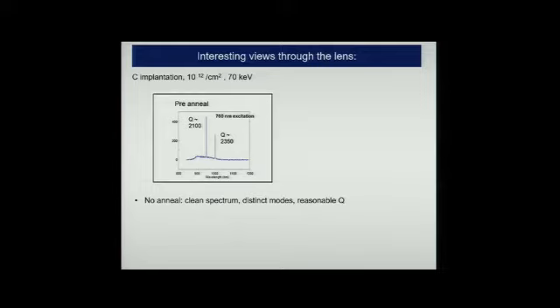we don't anneal. So we don't anneal. That means we've implanted. We've disordered the material a little bit, and yet it looks pretty good. The quality factors are pretty good. We get good signal to noise. So one would say, why bother to anneal?